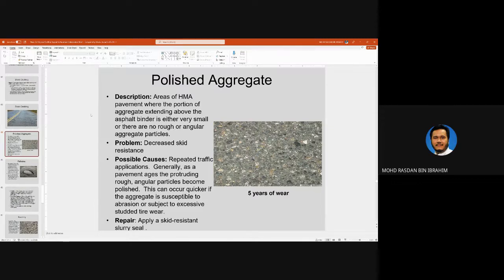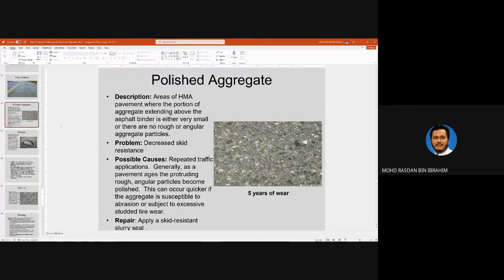So the cause is actually poor aggregate property, but it is being accelerated by traffic applications here. Repeated traffic applications. So generally, as pavement ages, the protruding rough angular particles become polished. Okay, so this can occur quickly if it is susceptible to abrasion or subject to excessive studded tire wear. So this is true for cold regions, snowy regions.